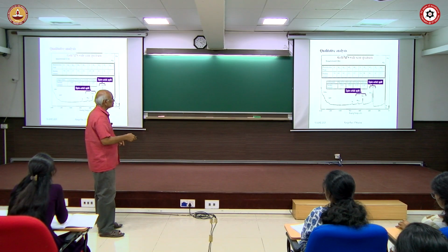It may be present in gold samples or in a gold ring. That spin orbit splitting will be the same. The energy difference will be the same. The peak areas, the area ratios of a core level of an element in different compounds, are nearly the same. Peak area ratios are also the same.